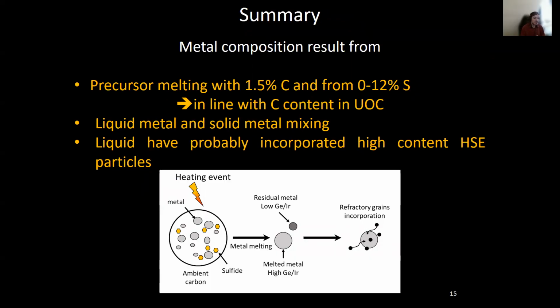So to sum up, the metal composition in ordinary chondrites can be explained by precursor melting that contained 1.5% of carbon and from 0 to 12% of sulfur. This is in line with carbon content in unequilibrated ordinary chondrites. Also, the liquid metal and solid metal have been mixed during that heating event, and the liquid has probably incorporated a high content of highly siderophile element particles that were refractory.